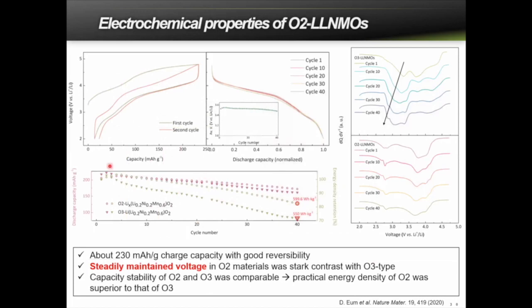To our surprise, we found that this O2 structure is very effective in retaining the energy density. This figure presents the first and second charge and discharge curves of the O2 layered material, which can deliver a capacity of more than 230 milliampere hours per gram. And the voltage profile of the discharge was almost unchanged over 40 cycles without a decrease of the voltage, indicating the success of our strategy.